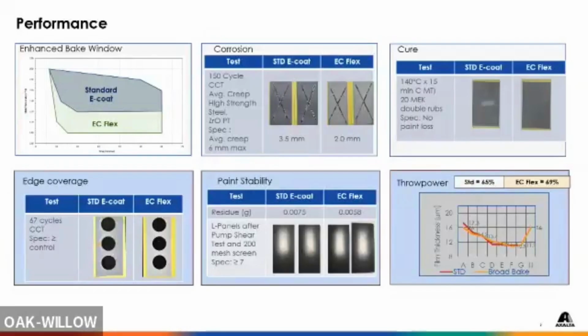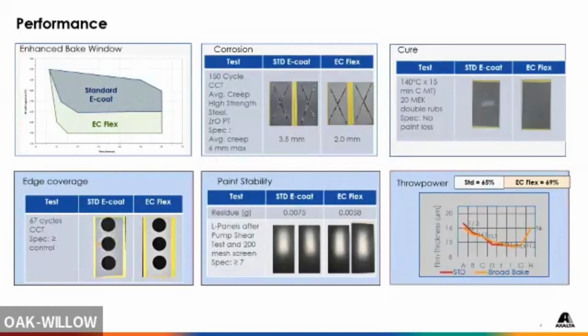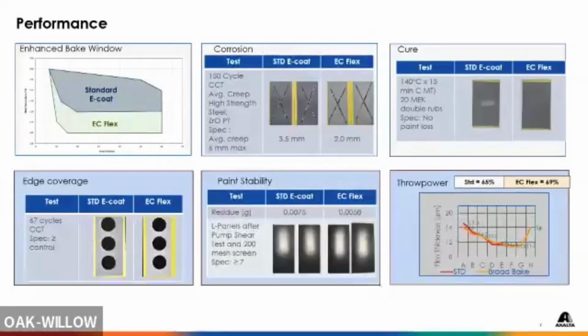Typically, cyclic corrosion goes out about 50 cycles, 40 cycles, where you go heat, humidity, room temperature, frozen, do that for 50 cycles, and then you check creepage or the production of corrosion products. In this particular one, the engineer wanted us to run it all the way to 150 cycles, which is almost 3 times the standard, just to run it to failure. Let's just run it to failure. And we only got about 2 millimeters of creep.